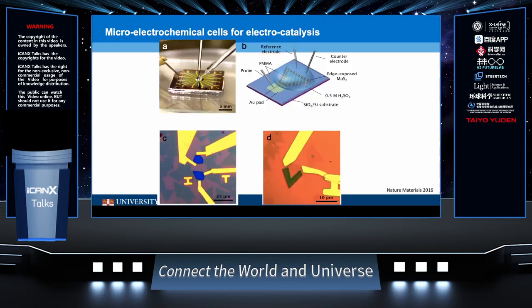So for example, we can measure the activity of the basal plane, or we can measure the activity just from the edge of MoS2. And so this is a very powerful technique, and it's been utilized widely now in the literature to understand the basic properties of catalysts and identify active sites on different types of catalysts.